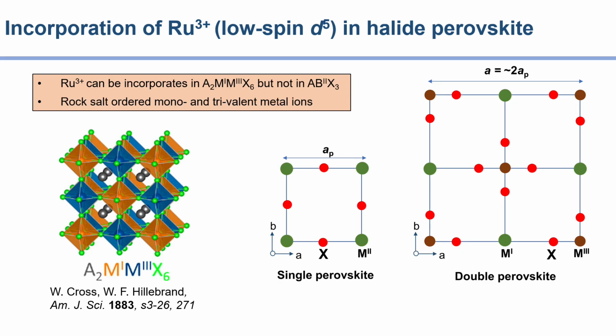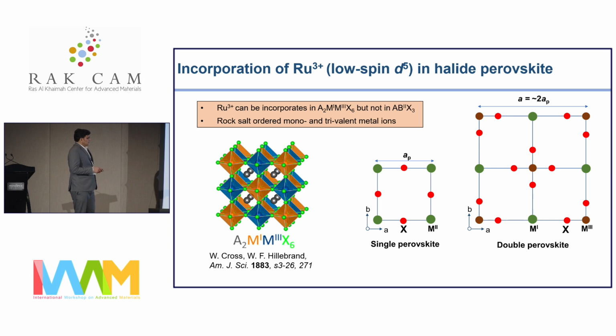Because ruthenium here is 3+, we cannot simply replace the 2+ metal in ABX3 with ruthenium-3+. So there is another type of perovskite, the double perovskite, which is very simple to understand: the B site is split into two sites. One of them will accommodate a 1+ metal, and the other a 3+ metal. That's where we can accommodate ruthenium. And to maintain charge balance, we can choose another metal which is 1+. Typically, in most cases, people choose silver 1+, or sodium, as Robert just mentioned.